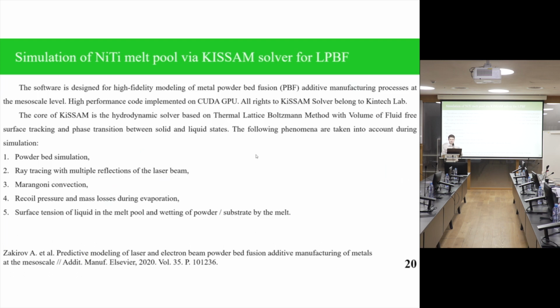This solver was developed by Kintech Lab, and it is a fluid dynamics solver based on the lattice Boltzmann method. This solver involves many important phenomena that happen during laser powder bed fusion. First of all, we have the powder bed. The energy deposition is done through multiple reflections between particles and substrate. Then in the liquid domain we have Marangoni convection. Because of the temperature gradient, we have recoil pressure that causes deformation of the liquid, and we also include surface tension for liquid and wetting of powder.